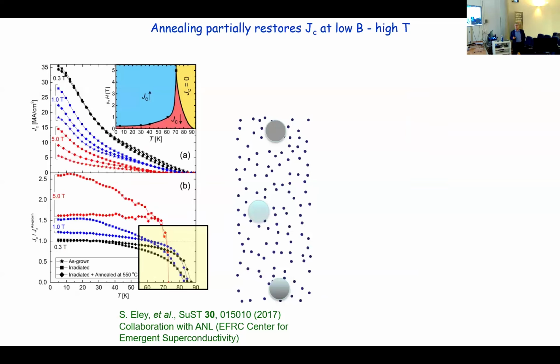I will not have time to go into detail with this, but we took one of those samples with oxygen irradiation that shows the large increases at high fields and low temperature, and some deterioration at low field, high temperatures. So the squares are the irradiated, compared to the pre-irradiation value; you can see it dropping way below it after irradiation.